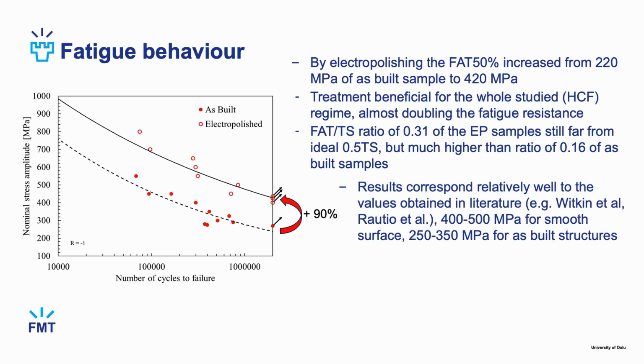But still the ratio of this FAT versus the tensile strength is quite low. It's lower than the ideal of 0.5 of the tensile strength, but it is still higher than the 0.16 of the as-built ones.